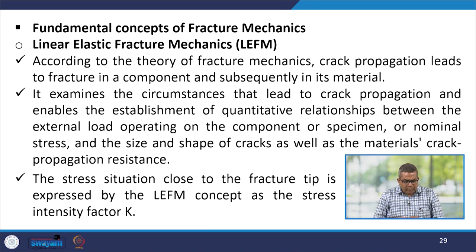Let us talk about the fundamental concepts of fracture mechanics. The linear elastic fracture mechanics, LEFM. According to the theory of fracture mechanics, crack propagation leads to fracture in a component and subsequently in its material. It examines the circumstances that lead to crack propagation and enables the establishment of a quantitative relationship between the external load operating on the component or specimen, or nominal stress, and the size and shape of a crack as well as the material's resistance to crack propagation. So, the stress situation close to the fracture tip is expressed by the linear elastic fracture mechanics concept as the stress intensity factor K.